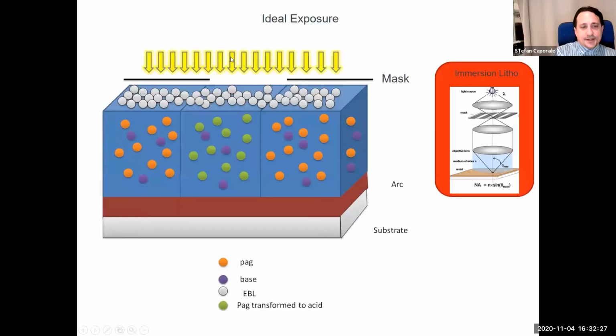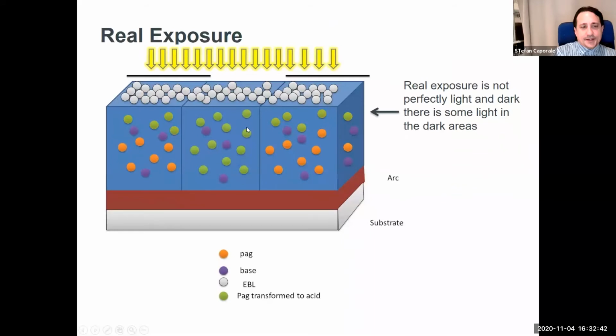So in an ideal exposure, your light comes through, and wherever you have light exposed, your PAG would transform into acid, represented by the green dots here, and then you would just develop that away. But the problem is that's not what really happens. In the masks, again, because we're phase shifting to get below the wavelength of the light we're using, you get basically really intense and less intense regions. So you end up getting, in the intense regions, PAG formed all the way through the film, but in the unexposed regions, they're not truly unexposed, they're just less exposed. So they have some acid being formed.